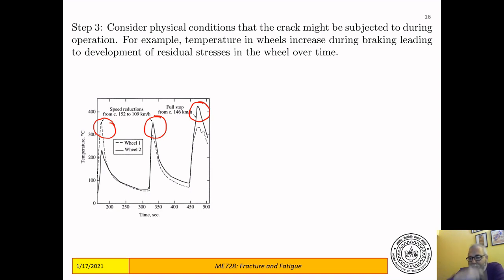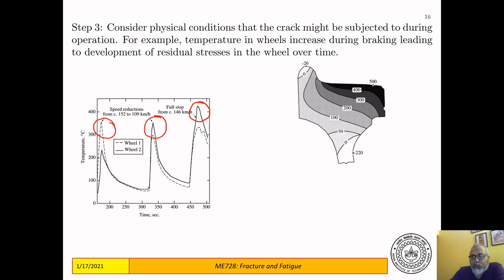This happens, remember, at the rim of the wheel where the wheel comes in contact with the rail. So you do some kind of analysis, maybe a finite element analysis, to figure out, if you are supplied this kind of friction force as in braking, what is the temperature distribution in the wheel. And what you see is, this is the rim of the wheel. This is the part that sits on the rail. So the rail comes somewhere here. So this is the rail. It's upside down actually. At this location, whenever it brakes, you see the maximum temperatures are attained here. So this is the region where you must put your cracks, because this is the region where the largest amount of thermal expansion would take place.